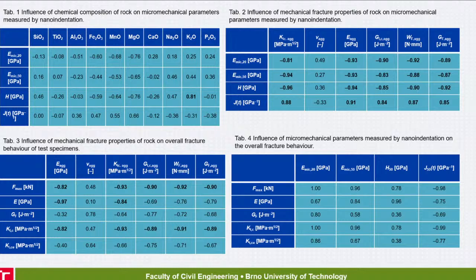So to determine the influence of chemical composition of rock on micromechanical parameters, we decided to simply use the correlation matrix. It's in table 1. Quite surprisingly, there is almost no strong or very strong correlation. It's mainly weak or moderate correlation. In table 2, you can see the influence of mechanical fracture properties of rock on micromechanical parameters measured by nano-indentation. There is a strong or very strong, mainly negative correlation, except for Poisson's ratio of rock material.